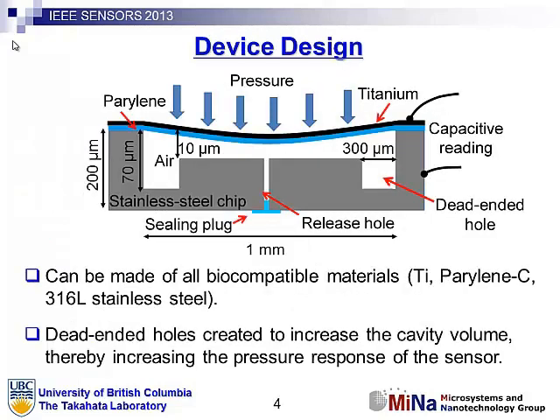So this is the particular device, and as you can see, the substrate is stainless steel. The lateral dimensions are 1 millimeter by 1 millimeter, and the cavity depth itself was 10 microns. And there are some holes in the corners to increase the volume inside. The reason being is that when you apply an external pressure and bend the membrane, it's really the pressure inside equalizing to the external pressure that prevents further deflection of the membrane in this case. So if you increase the internal volume, you allow more deflection of the membrane and a better sensitivity of the device. And the materials used were 316L stainless steel.